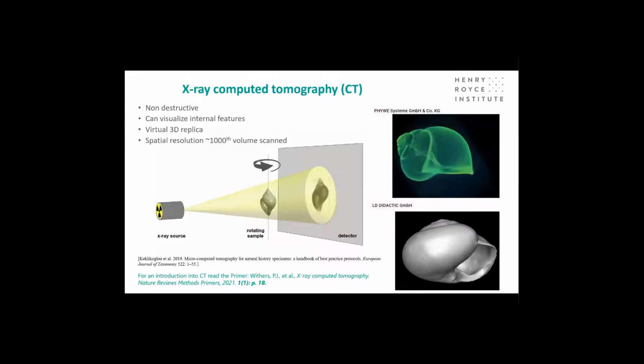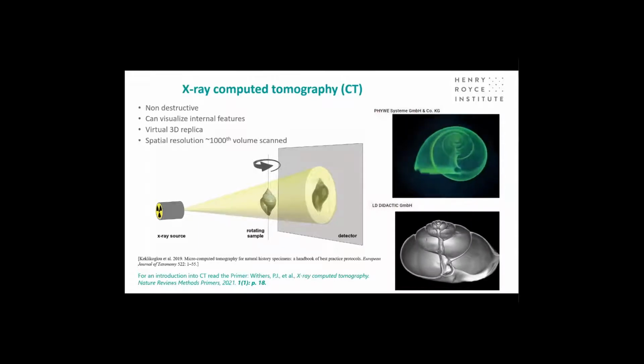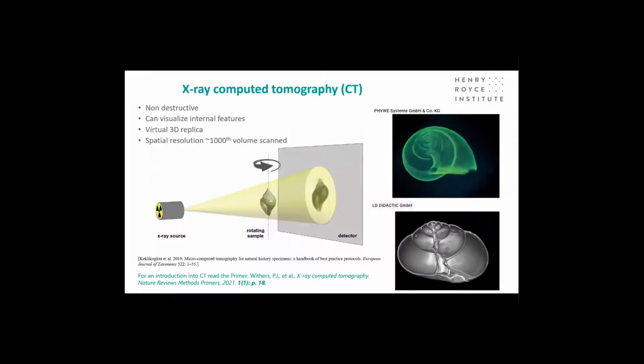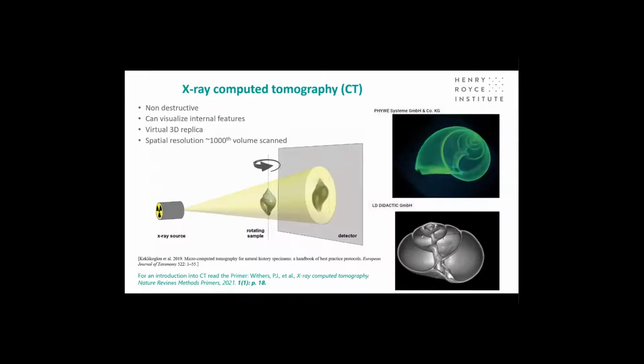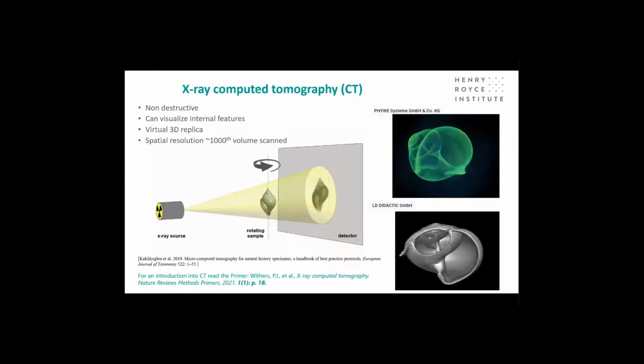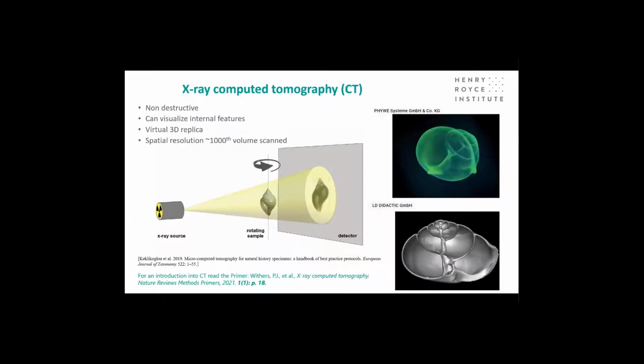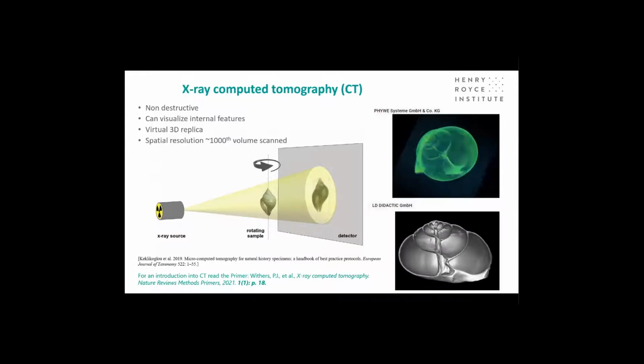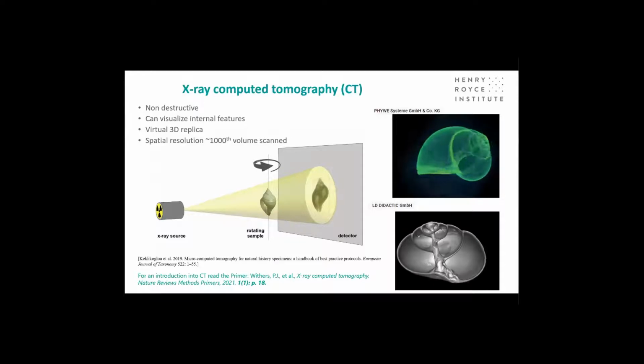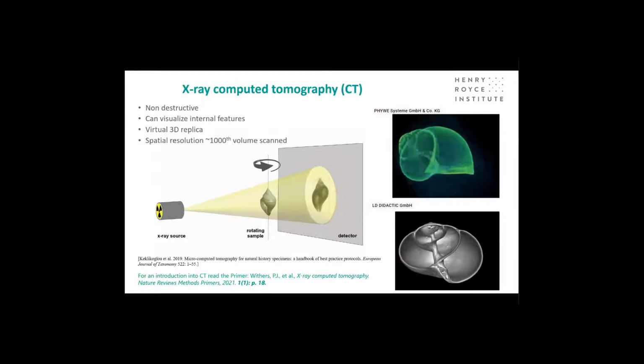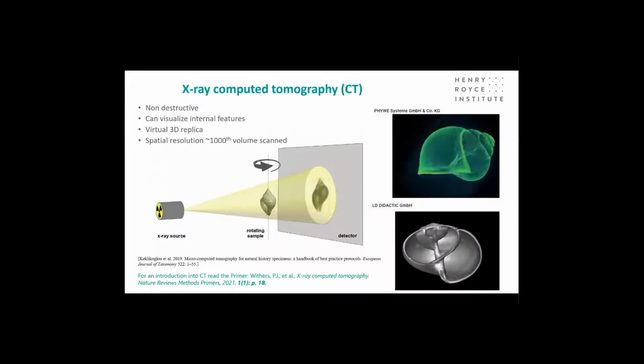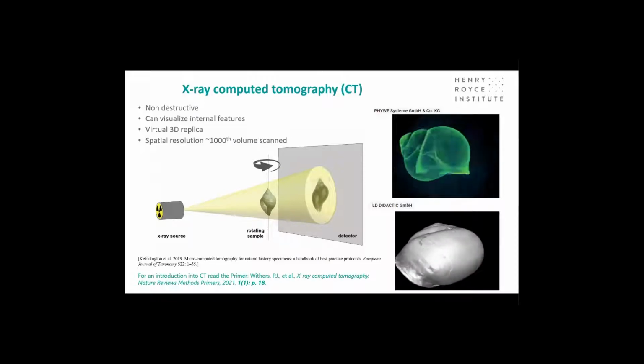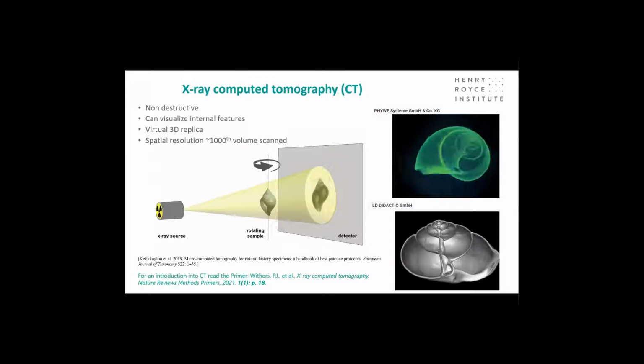Now, following the first lecture, I guess it's useful to stand back and ask, how does CT work? Computed tomography: at least in materials science, you tend to rotate the sample. In medical science, you tend to rotate the scanner and leave the person stationary. But in materials science, one tends to rotate the sample and collect a series of projections, usually between 500 and 3,000 projections. It depends a little on the resolution and on the number of pixels in the detector, but basically somewhere between 500 and 2,000 or 3,000 projections. In some cases, when one wants to go very fast, you might reduce the number of projections, in which case you generally need special reconstruction algorithms to recover the quality that you want.